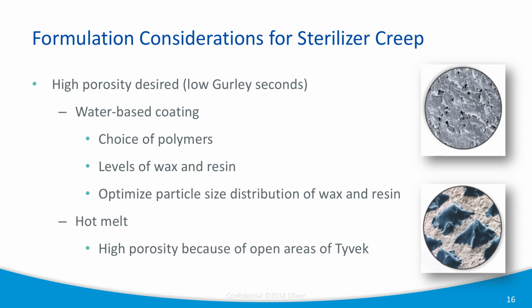Also the levels of wax and resin. Generally when you get higher levels of wax and resin, that gives you a more open structure, and that can increase your porosity as you desire. And then a third thing is optimizing particle size. So this is really a processing thing when we're producing the adhesive. By adjusting the parameters, we can control the particle size. We measure the particle size, and if you get those particles too small, they start to close up those small pores. So that's an important consideration.